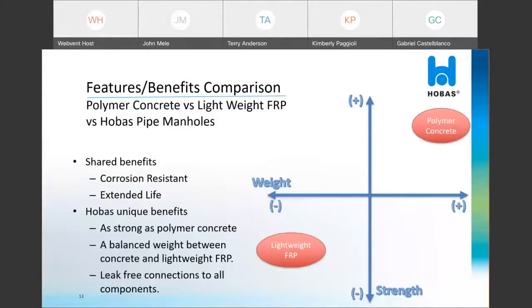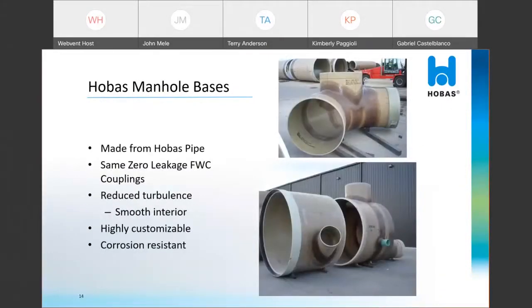Hobas Pipe is able to balance these two key features. It is just as strong as polymer concrete, but has a lighter weight. This thicker wall results in a higher buckling capacity, while also having enough weight to overcome flotation forces. The first part of the Hobas manhole solution is the T-base. This is nothing new, as for decades this has provided a uniform, smooth transition at manhole locations. This is because both the base and the joint are made of the same Hobas pipe and the FWC coupling as the rest of the sewer line. This reduces turbulence and ensures a zero leakage connection.